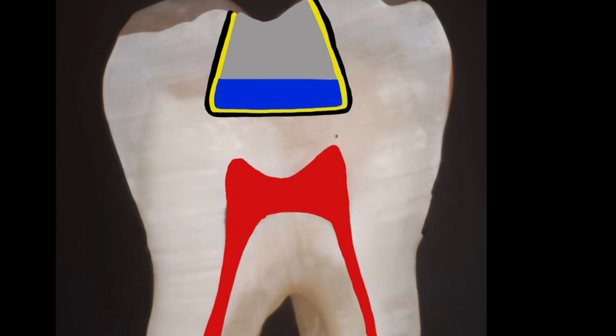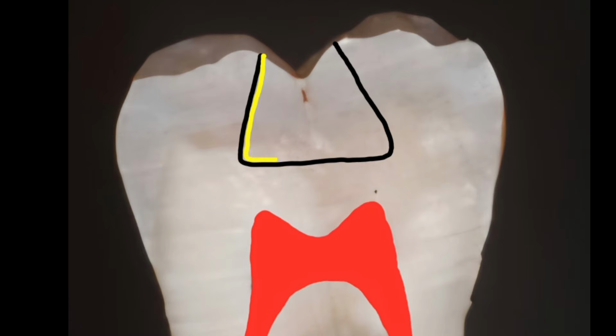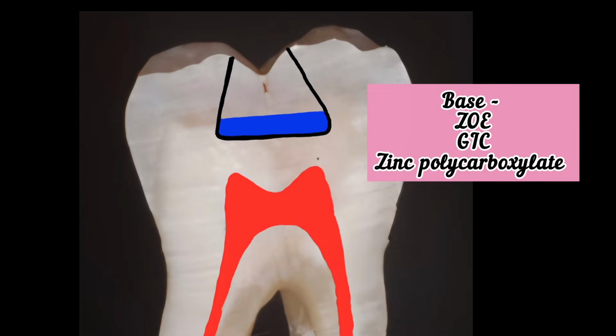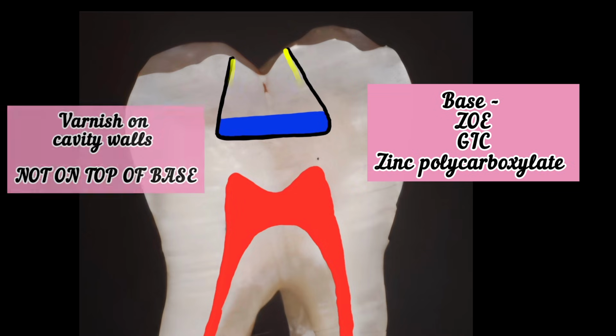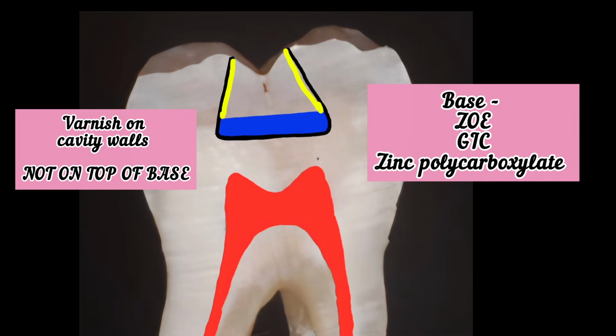So whenever we use zinc phosphate cement, we apply varnish prior to the application of the zinc phosphate base, while when we use other dental cements like zinc oxide eugenol, zinc polycarboxylate, or GIC, the varnish is usually applied after the base application and after the base hardens.